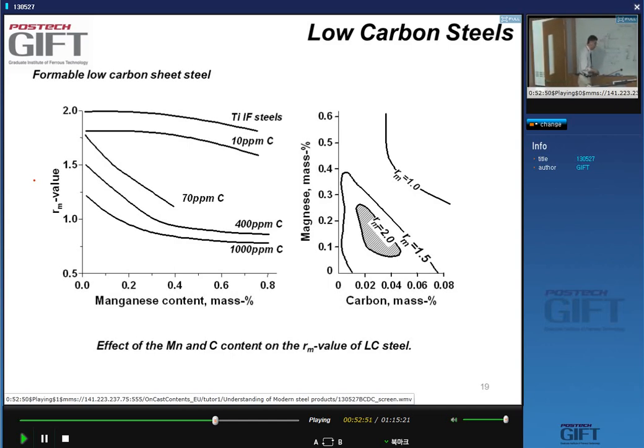Now, when we have alloying elements in solution together with carbon, these alloy elements may or may not interact with each other. There is a very pronounced interaction between carbon and manganese, yes? And although we do not add much manganese, if any, in these low carbon steels, the manganese is there, and the level is typically 0.15 to 0.2. And the manganese has the effect that it keeps the carbon in solution because it attracts the carbon, yes? So the carbon sticks to, or close to, the manganese atoms, and so it slows down the carbide formation as a consequence.